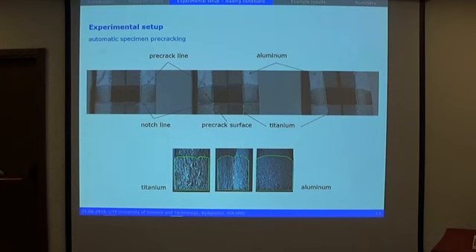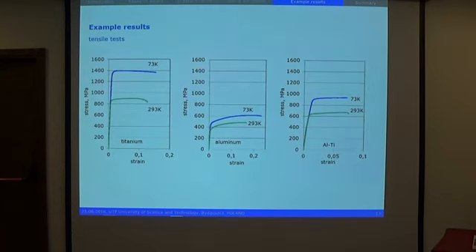Yes, and what is the reason? Of course, we have used the fatigue process for initiation of the cracking process. It means that we have a few different problems. The first one is that the crack initiation phase is different for aluminum alloy and for titanium alloy. The crack growth rate for aluminum and titanium is also different. So if we want to obtain similar crack length in the aluminum and titanium, we should sometimes make a few or more than a few tests.